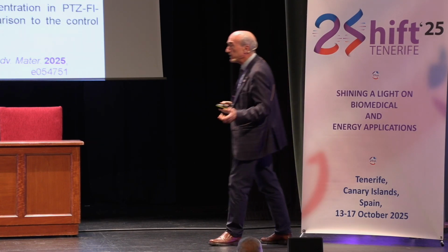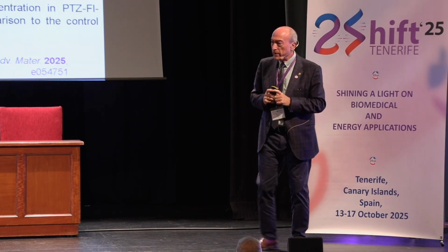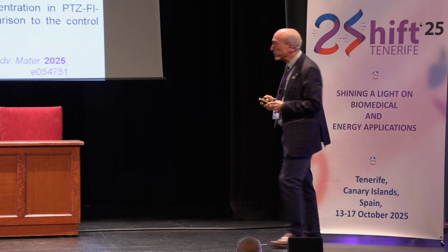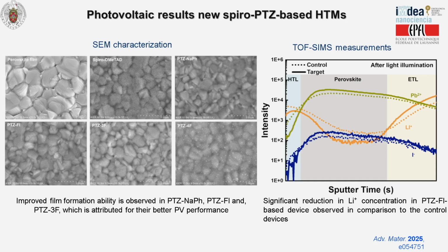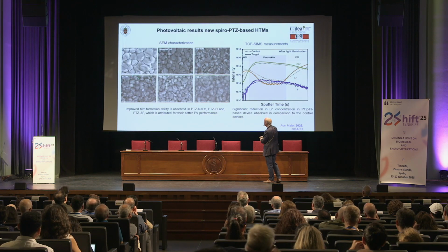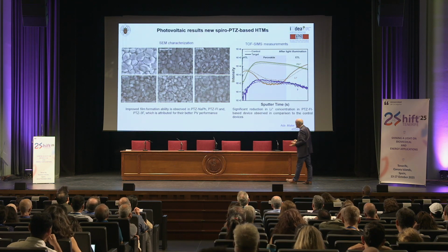So just to prove this, the referee said, you must fabricate a mini module. And that is one of the reasons why it was published later on. Also, this experiment was a time-of-flight secondary ion mass spectrometry in this area, which nicely supports the theoretical study by Enrique, saying that the lithium is decreased in the transporting material, thus preventing its presence in the perovskite. Also, an experiment with the SEM. I will not go into detail, but you can see here that when you compare with the spiro, this is the pristine perovskite, spiro, but when you go to the system with the fluorine, or this one with the naphthalene, it's a little bit smoother.